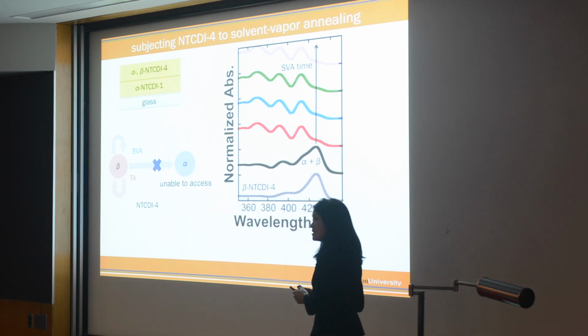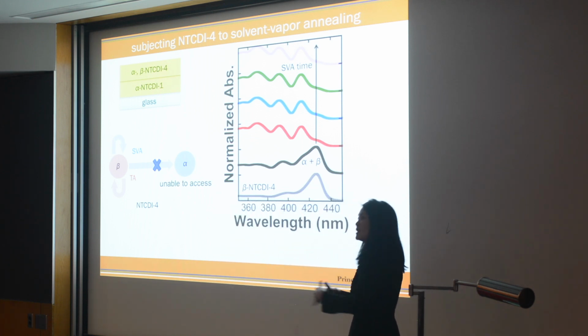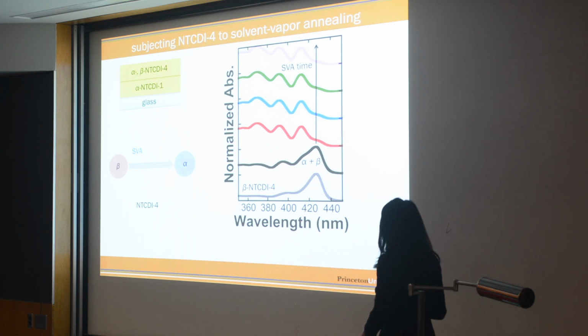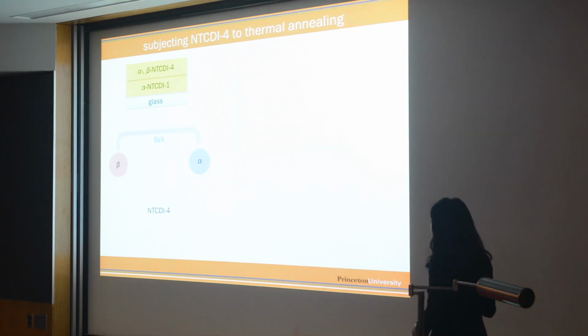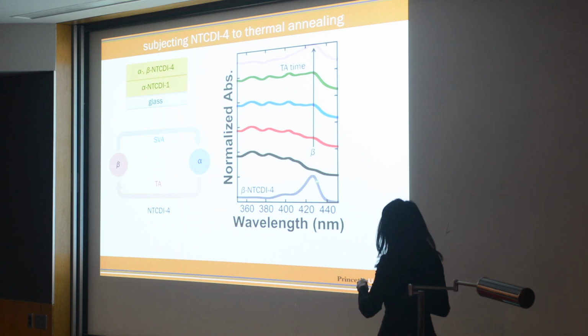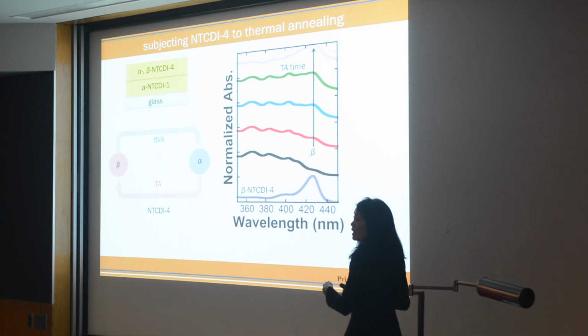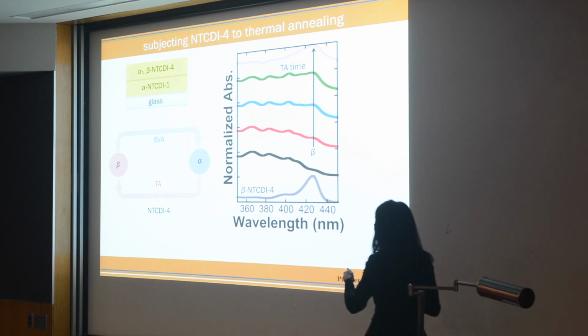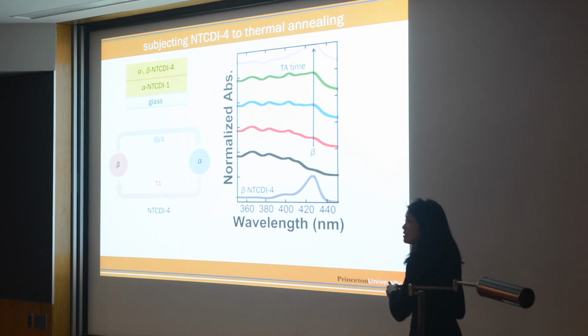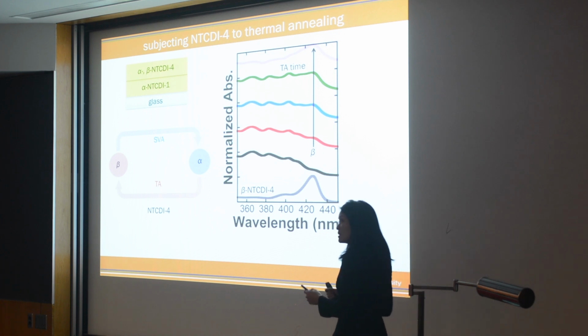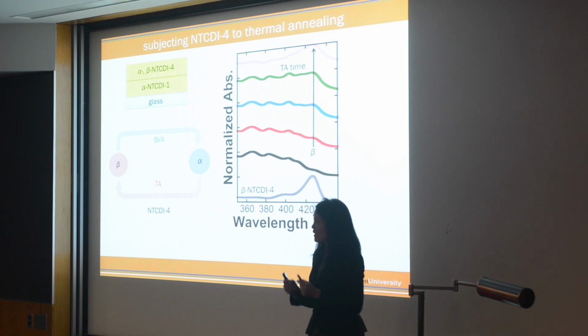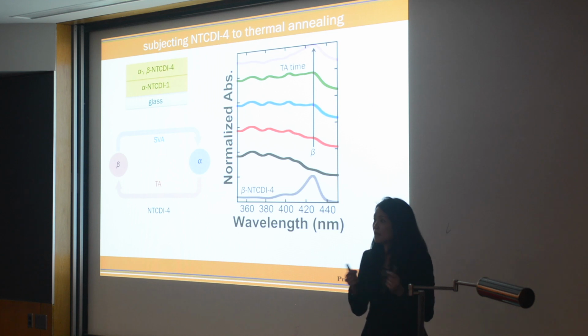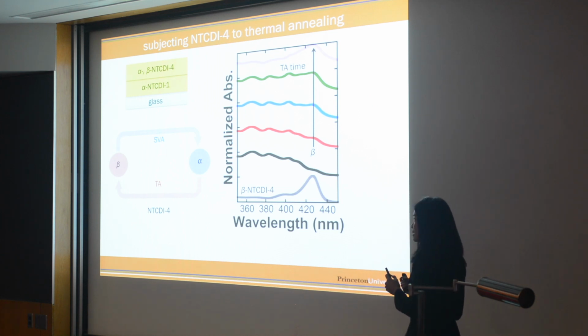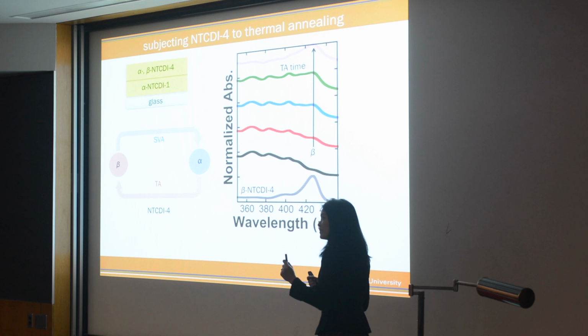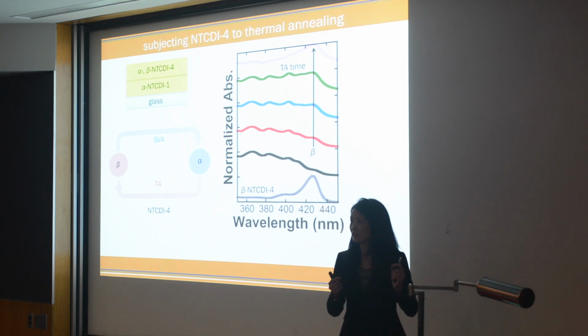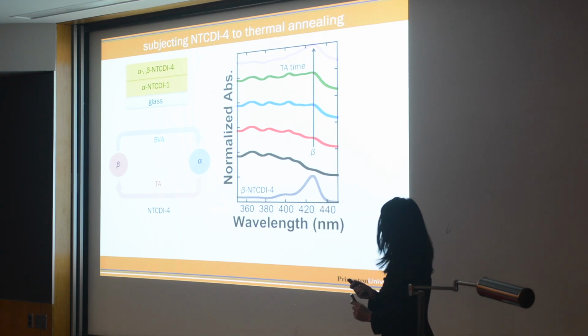Because alpha is now present, the beta is willing to convert to alpha. Similarly, we can go the other way around. Okay? We take that film, and we now thermally anneal, and we can convert the alpha all the way to beta. So again, these are important control experiments because they tell us that the barrier that we were measuring before, the inability to convert between these different polymers, is really a nucleation barrier. Once we can overcome that nucleation barrier, the conversion's easy, so the growth part is easy.